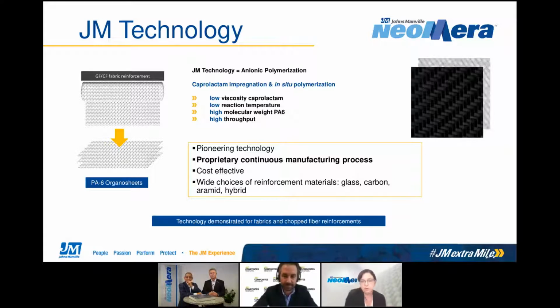So in order to create that 3 millimeter organosheet that you saw earlier, we start with a couple of layers, so 2 or 3 layers of fabric that we impregnate at the same time. So the polymer is forming this structure. There's no risk for delamination, and this is why you're seeing the good performance in that open, close, and in a sense fatigue cycles that Jan was describing. So this is how we break the barriers by innovating, and that's a technology that has been developed at the Johns Manville Technical Center in Colorado.